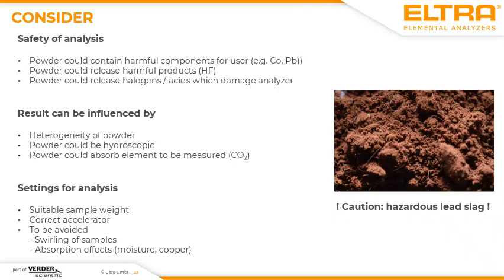It's also possible that, for example, your sample could release hydrofluoric acid. That means, for example, you can get corrosion inside the analyzer, and the release of hydrofluoric acid may be hazardous for your environment. The other thing is that some samples, for example, which contain acids or a high halogen content, could release elemental halogens and also acids like hydrochloric acid, which could damage the analyzer and could also be harmful for you.